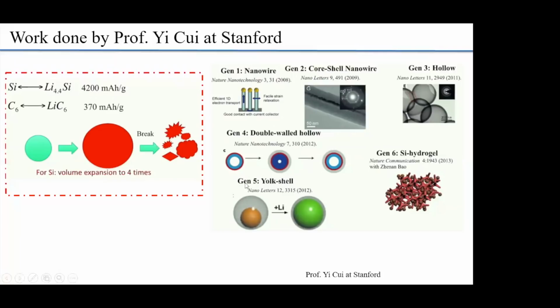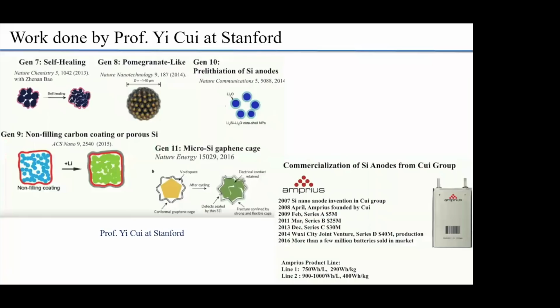It remains stable. And then they came up with the yolk shell, where basically what you see is silicon covered by a scaffold. It can expand and contract, expand and contract. But none of this is done at a commercial scale. So they kept improving. Generation 7 is self-healing. They could heal even if it cracks. It can heal back. Then they came up with a pomegranate-like structure, an agglomeration of small particles which are like yolk shell, and then they were able to do pre-lithiation of silicon anodes.